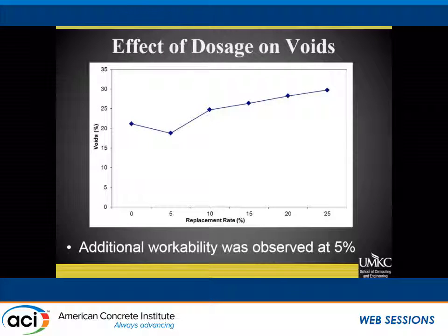So these are averages of 3 samples. This is void content as measured by ASTM C1754, so the standard Pervious concrete void content. And so we saw that we did indeed have a decrease in voids at 5% silica fume dosage rate because we had a little bit more workability. Above that, 10% is a pretty high dose, 15, 20, 25. It got stickier, void content rose accordingly.